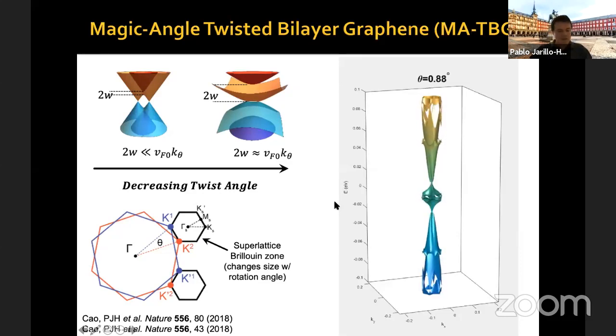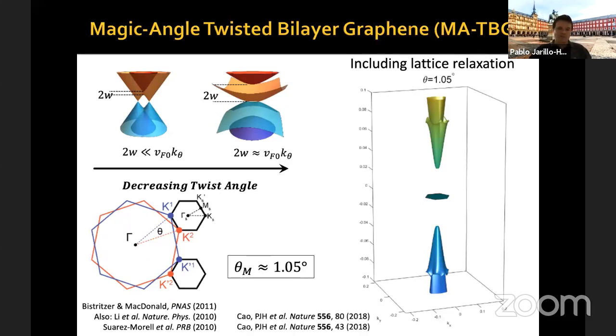Okay, and now, when you make devices at about this angle, again, this is not a snapshot of one of those frames in the previous video. In this case, for 1.05 degrees, including these lattice relaxations, you can see there is this very flat band. And then we have these remote bands with a higher dispersion at low energies. Now, if we make devices and place the chemical potential in this flat band, interesting physics happens, okay?